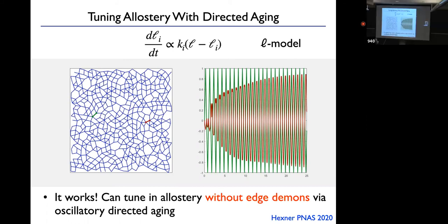So bonds that are affected tend to be closer to the source and target. But this is actually something that we've spent a lot of work on. We've developed persistent homology analysis to understand what we are doing when we change these bonds. How does changing these few bonds actually give us this collective response? It turns out that we get an answer from persistent homology, which says that the system actually breaks up into sectors of nearly uniform strength. If I treat these sectors as rigid bodies, the difference in their strain is what gives us the allosteric response.